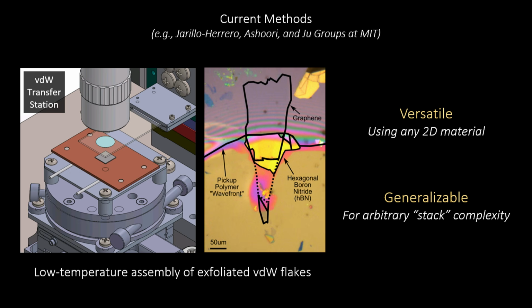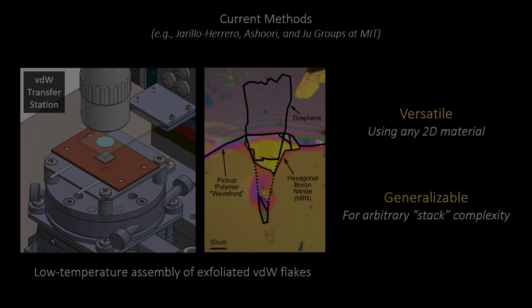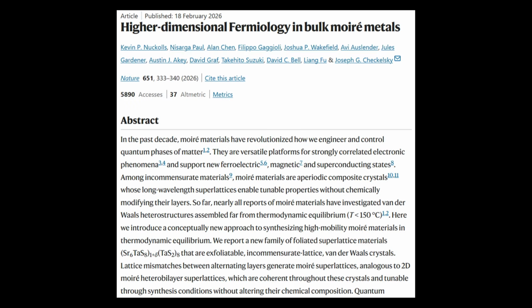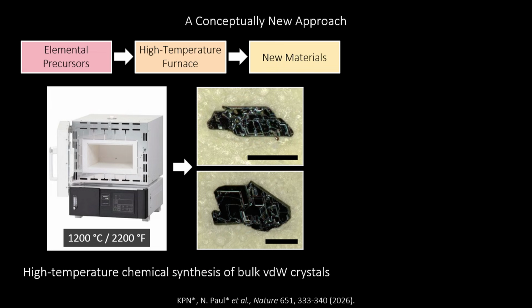It's also generalizable. If I have a Moiré material that has multiple twisted interfaces, I just pick up more materials and incorporate them into the stack. And so this has been a really essential tool for 2D research. But today, my teammates and I have introduced a conceptually new approach to designing high-quality Moiré materials using the tools of solid-state chemistry to stabilize those crystals as well as tune their lattice properties. So this offers us a conceptually orthogonal but complementary approach to generating Moiré materials using the high-temperature chemical synthesis of bulk van der Waals crystals.